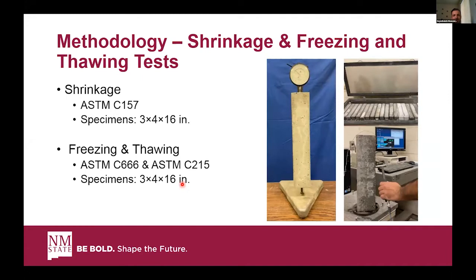For the shrinkage test, ASTM C157 was used, and for freezing and thawing, ASTM C666 and ASTM C215 were used. And these tests were performed on 3x4x16-inch prismatic specimens, as you can see again in the figures.